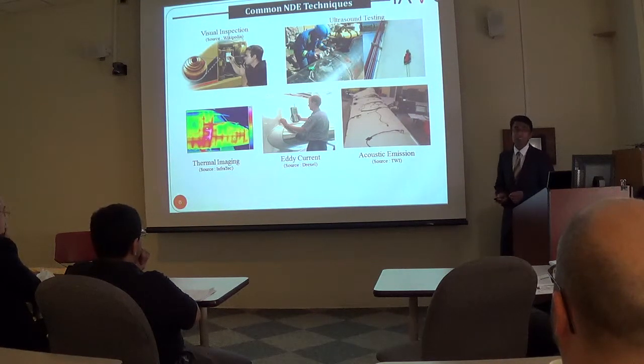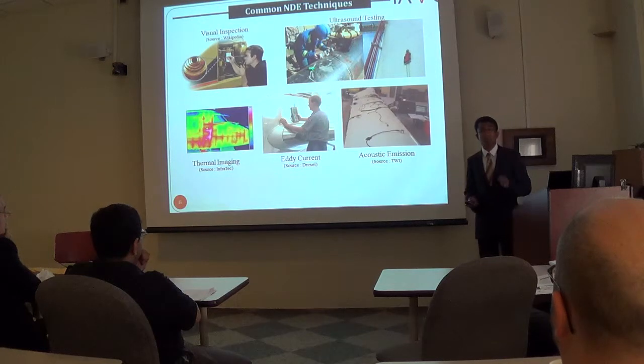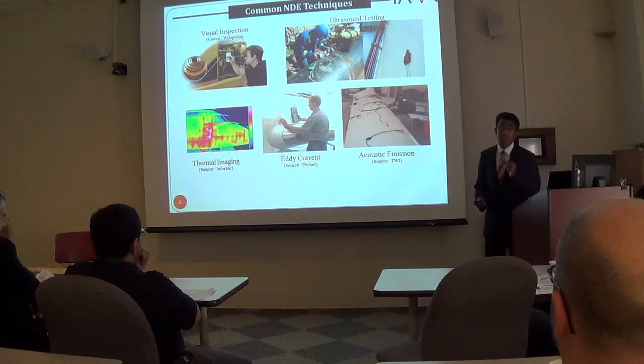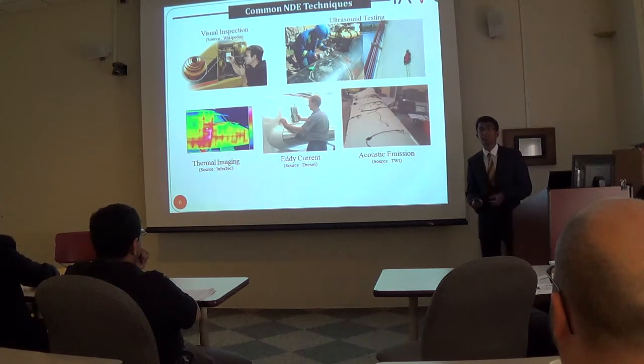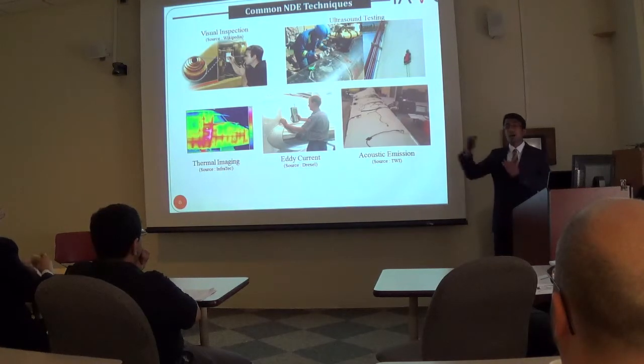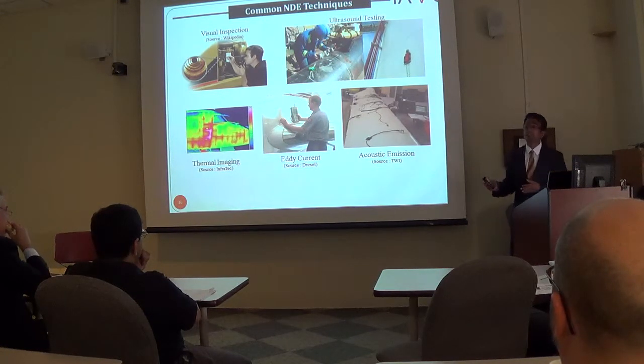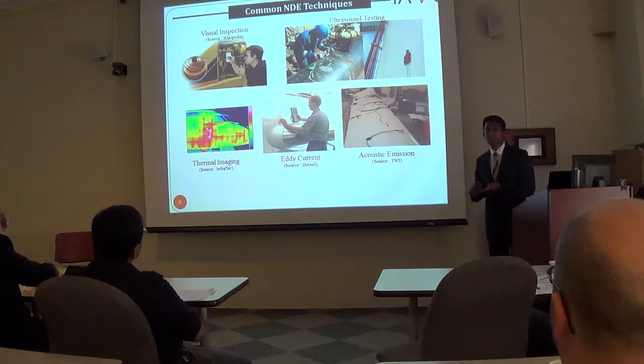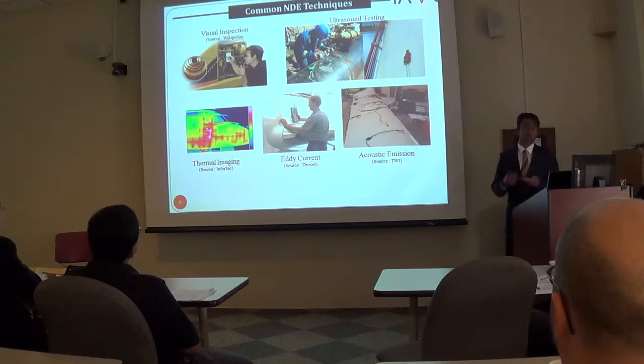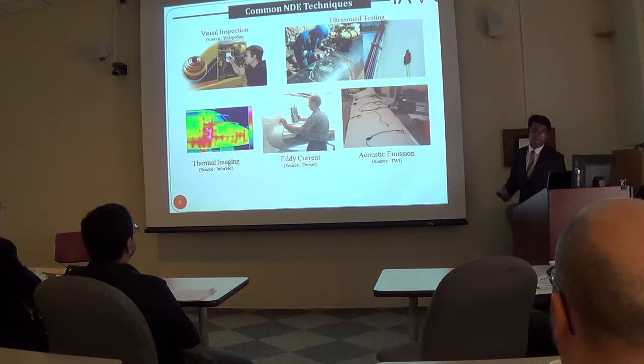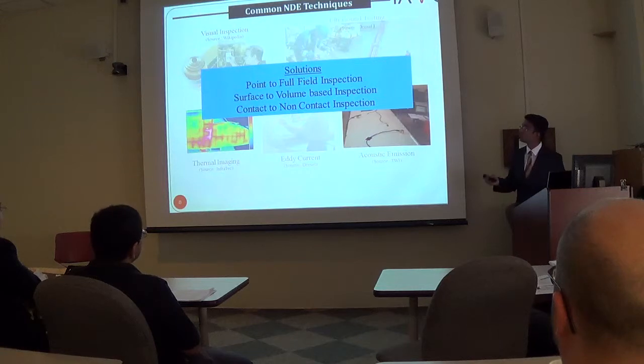Secondly, acoustic emission can also be utilized in real time to detect the region of damage or the location of damage, which can then be utilized as an intelligent method to direct other extensive NDT methods to specifically look at certain regions, thus saving time and cost for damage inspection. These solutions range from point to full field inspections, surface to volumetric-based inspection techniques, and also contact to non-contact inspection techniques.